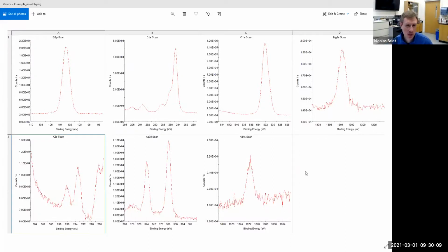So I couldn't really do good quantification. I was really pressed with time, but I did run some scans at the surface of the sample. What you can see is not like EDS where you have the whole spectrum growing. You really have to scan every element with a range of energies. So that's the 100K sample, okay? And what you can see is the usual suspects for glass, silicon oxide. You see a lot of carbon because the surface is so surface sensitive that any contamination or residue at the surface will show clearly.